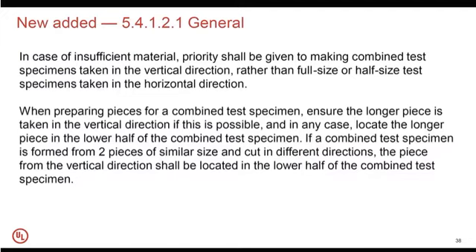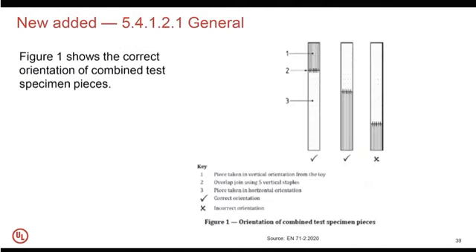If a combined test specimen is formed from two pieces of similar size and cut in different directions, the piece from the vertical direction shall be located in the lower half of the combined test specimen. And in the figure 1, there is an indication of the correct orientation of the combined test specimen pieces, with both the correct orientation as well as the incorrect orientation.